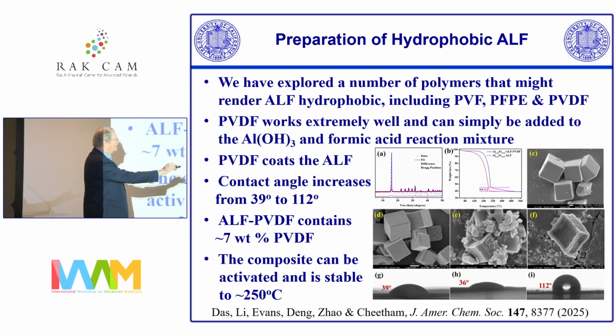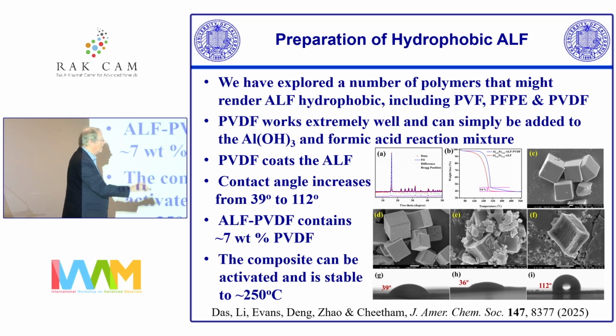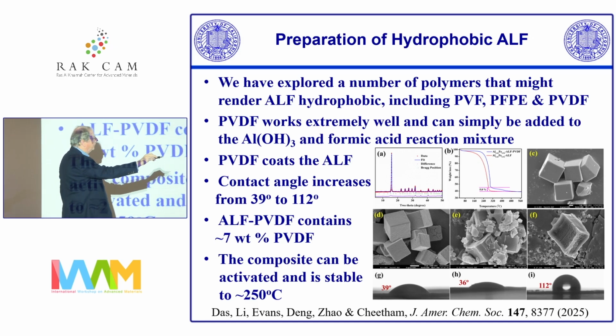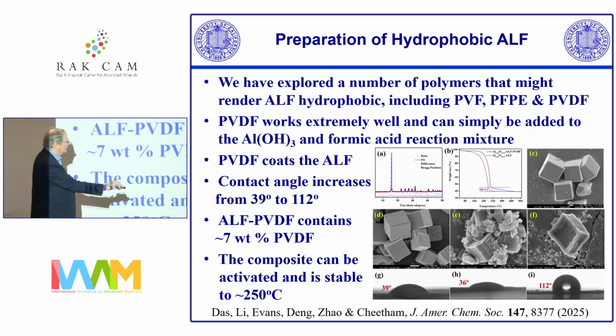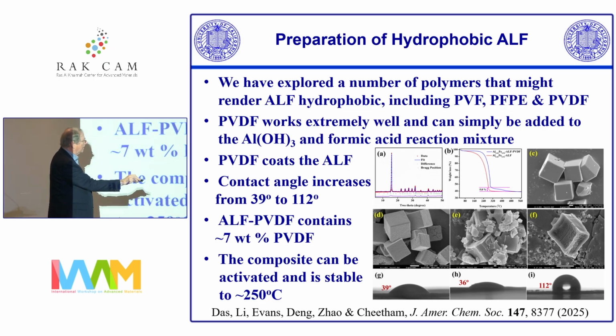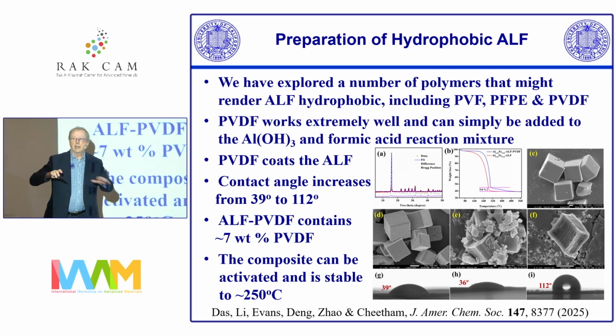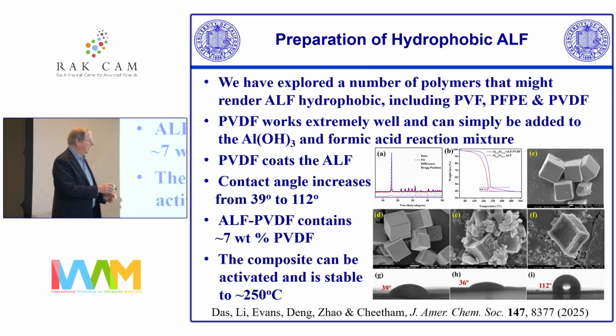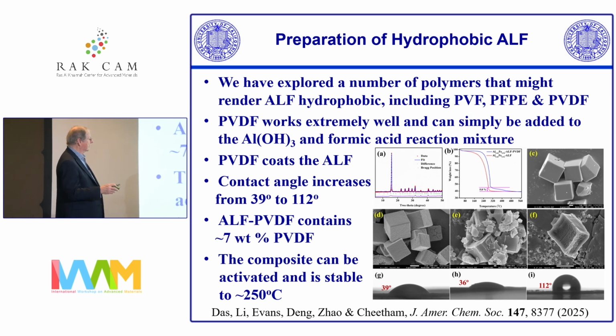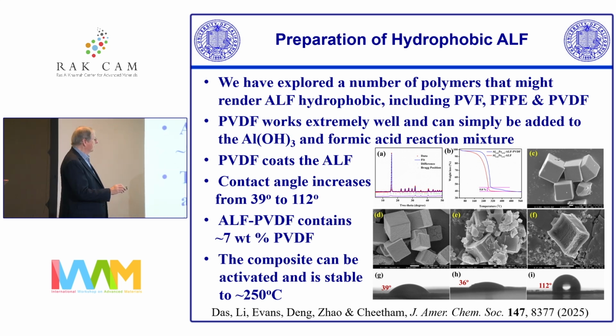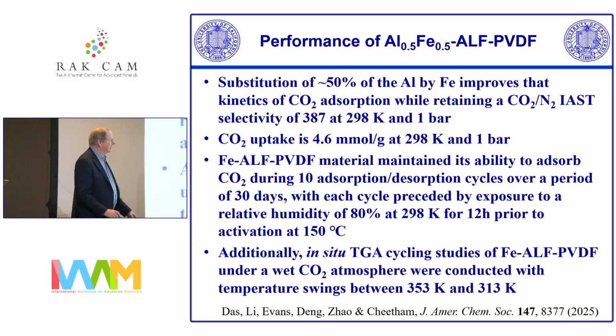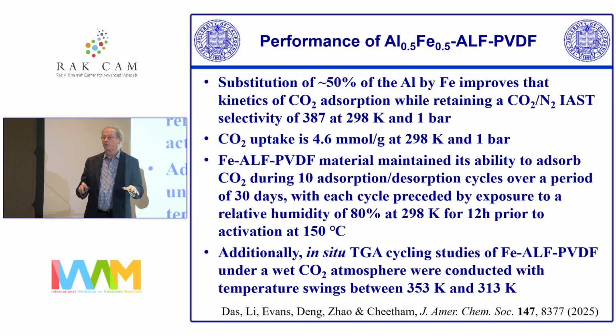And so these are the crystals that you get in the absence of the PVDF, and this is what they look like in the presence of the PVDF. But you can see the contact angle goes from about 39 degrees for the regular ALF to 112 for the PVDF-coated material. So it's highly hydrophobic. And I won't go through all the details of the characterization. It's still stable to 250 degrees C. What this slide tells you is that it has the same performance and slightly better performance even than the regular ALF material without the PVDF. And we need about 7% of PVDF, so it doesn't dramatically alter the costing in terms of the materials.